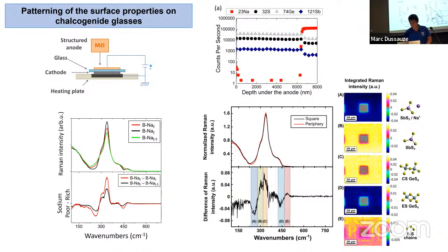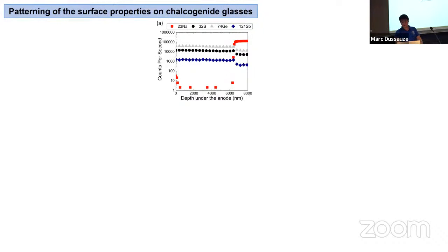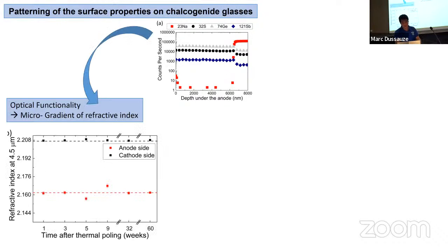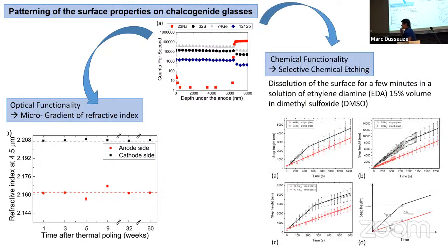So now let's go further. What can we do with this depletion layer and with this change of compositions? The first thing we can do is quite easy. We can look at the refractive index change. And if you look at the index from the anode side to the cathode side, you have a huge difference of 5×10^-2. So that's the first very nice property that you can tune, the refractive index. The second one that you can tune is the glass chemical